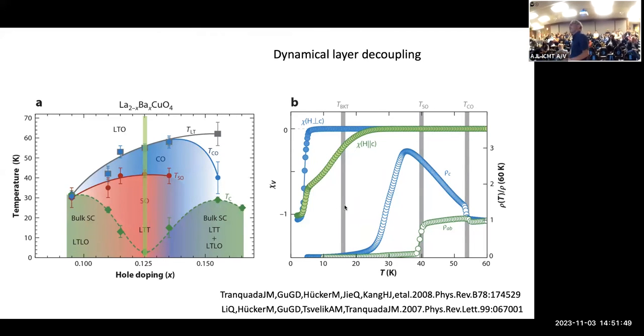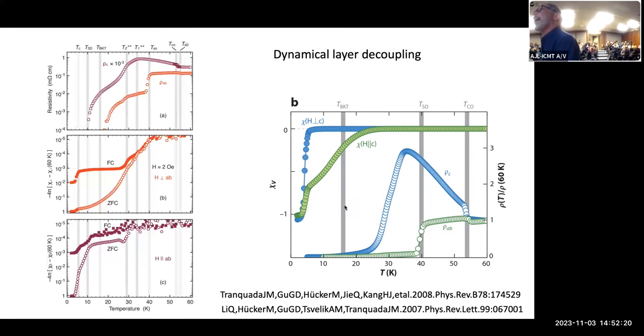These two curves are the magnetic susceptibilities measured with the magnetic field either perpendicular to the AB plane, to the copper oxygen plane, or parallel to the copper oxygen plane. The main thing I want you to focus on is that the Meissner effect, the full superconducting state, occurs at a much lower temperature, 4 Kelvin in this particular material. Okay, so that's very dramatic.